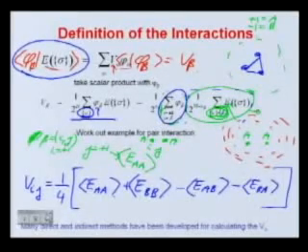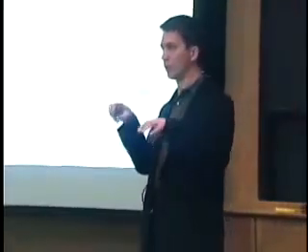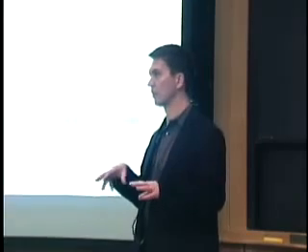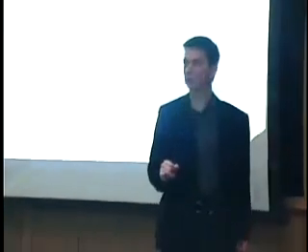And then what you're going to find is that essentially all of the pairwise sum cancels in this difference except the AA interaction, the BB interaction, and the AB interaction. So if you do just a pairwise energy expression, and you should try this once, it's very pedagogical, and the atoms don't relax away from the lattice, then you'll find exactly that these are pair energies, pair potentials.